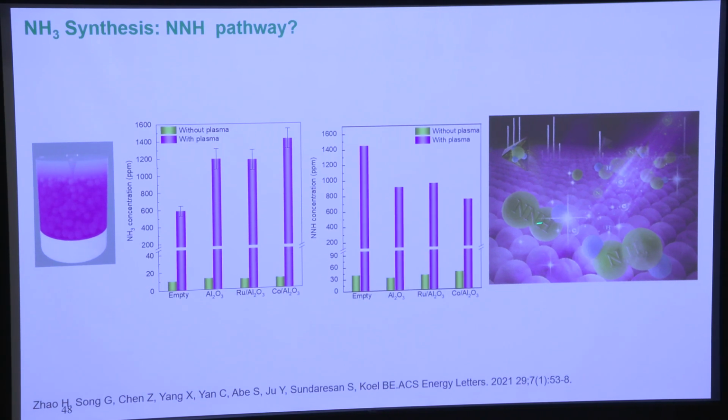So what do we conclude? That the plasma gas phase chemistry forms NH, NH2, and N, and that provides a rate limiting reaction to the surface. So now they have two debates: the NH group or the N atom becomes rate limiting. So which one is true? I think this experiment suggests that maybe there are multiple mechanisms.